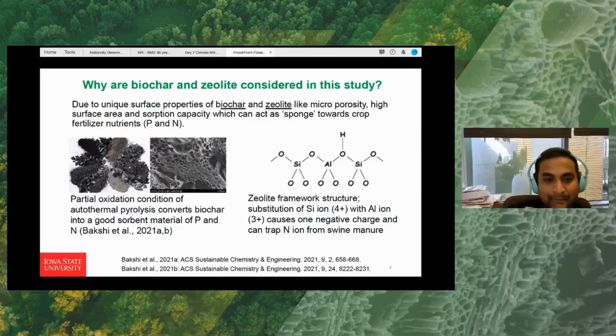On the right side, the zeolite structure: substitution of one silicon ion with an aluminum ion causes one negative charge, and that negative charge can be utilized to trap nitrogen ion, especially ammonium, from the swine manure.